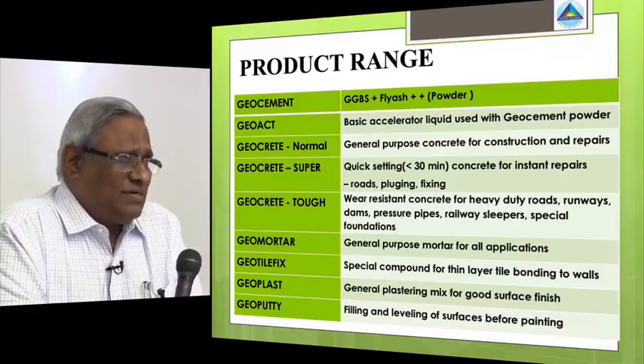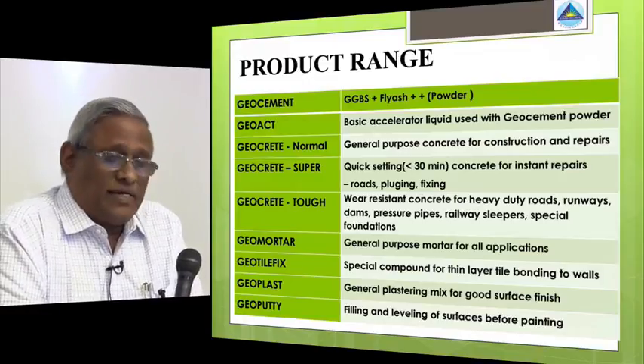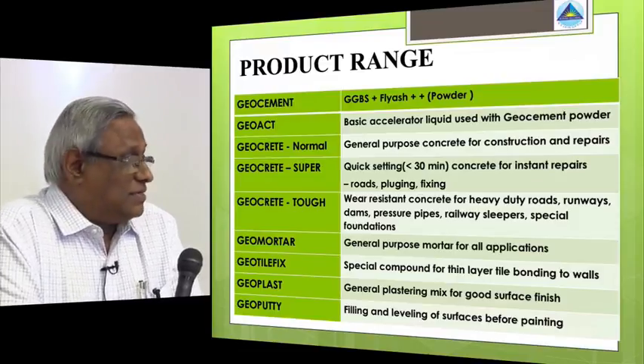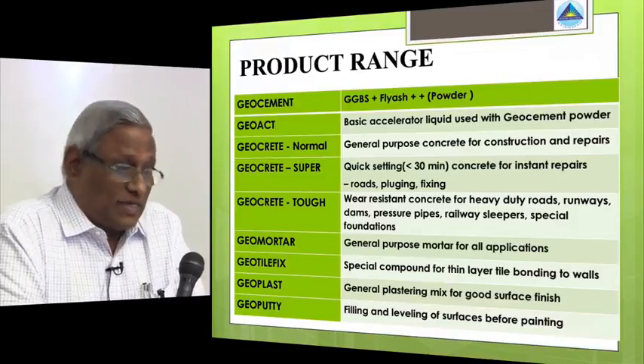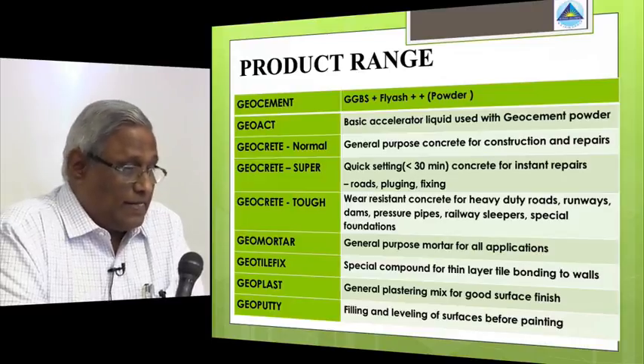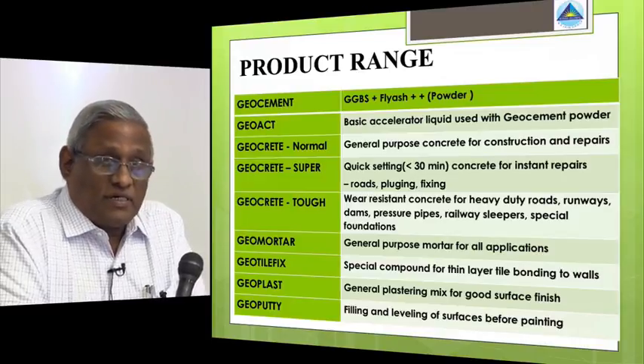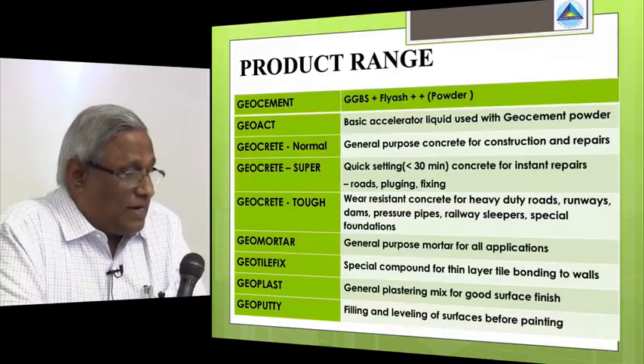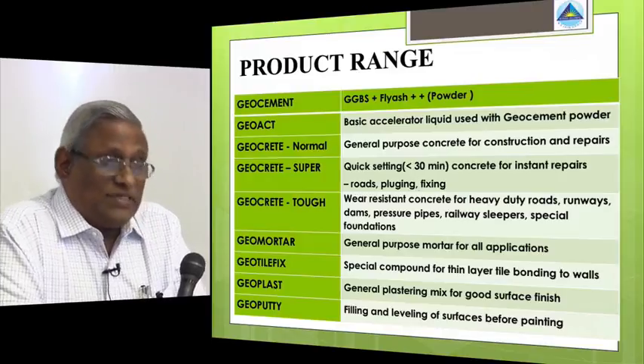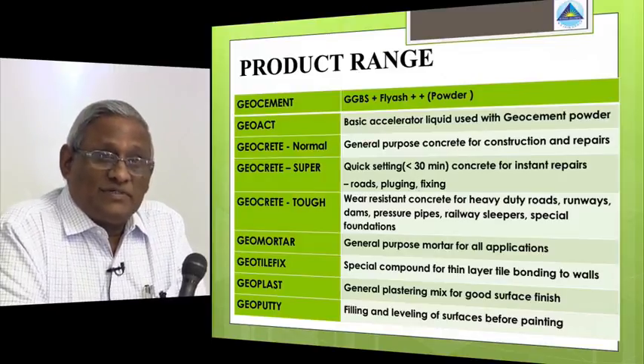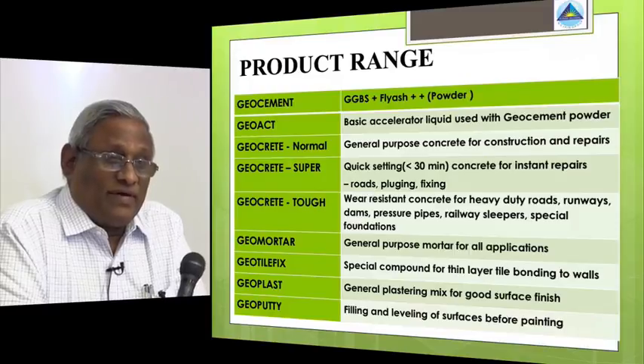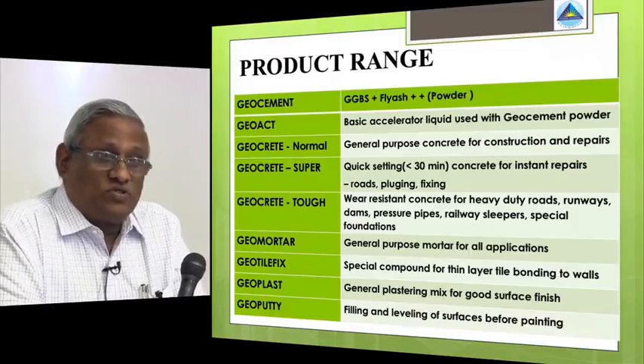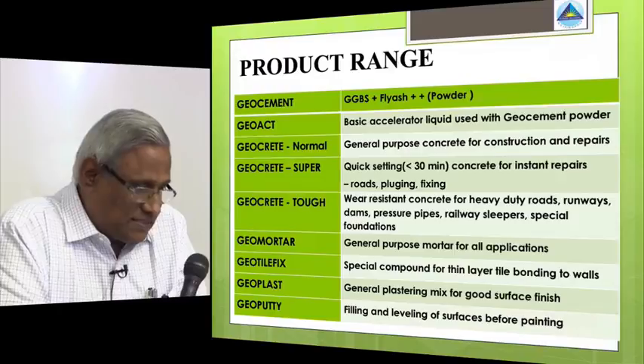Geomortar has worked very well, and we have trained over 30 masons to work, and they have in turn trained about another 100 people, and it's a very big achievement by using this Geopolymer mortar. And then our compound on fixing the tiles has come out very well. We have a mortar joint of just 2 to 2.5 millimeter thickness.